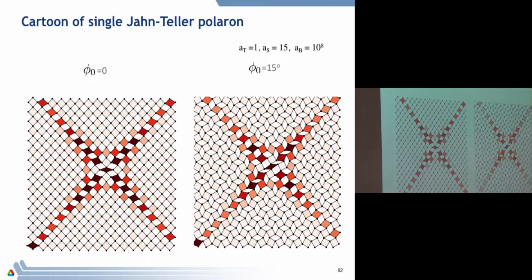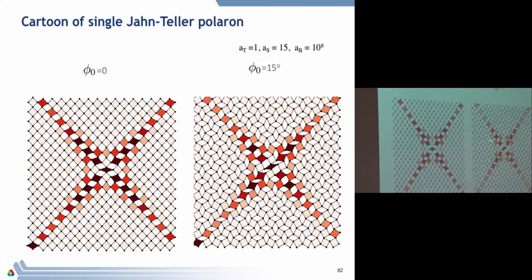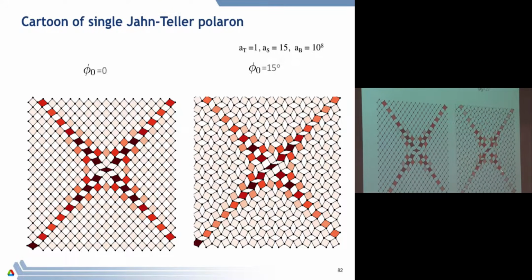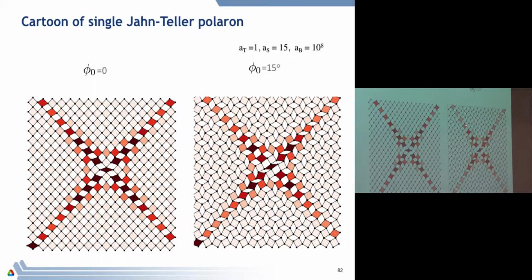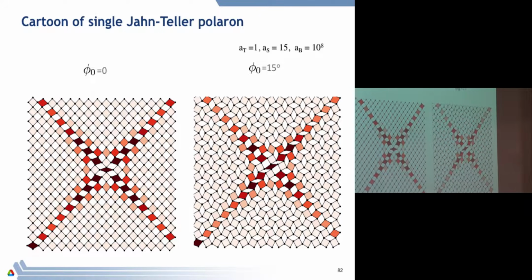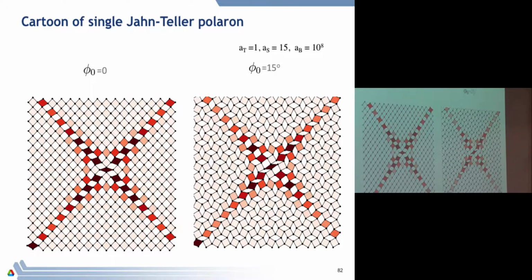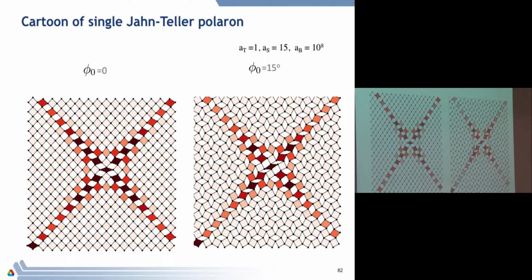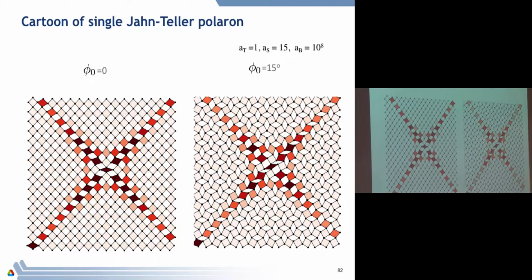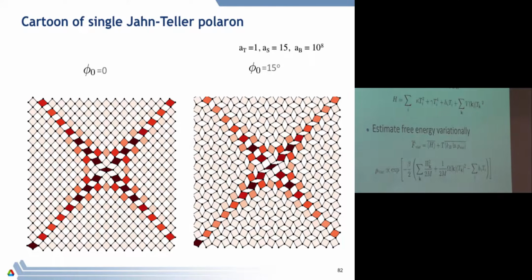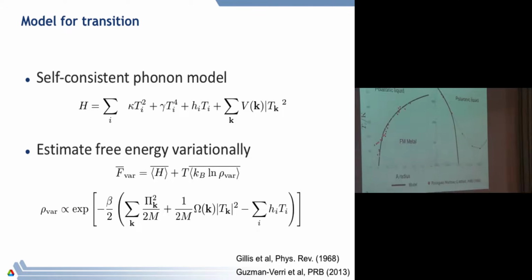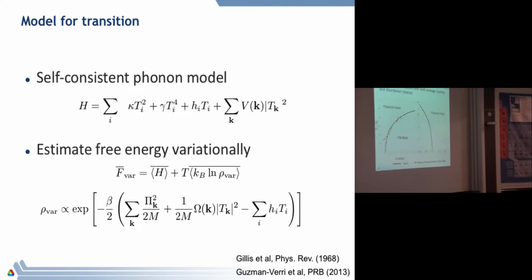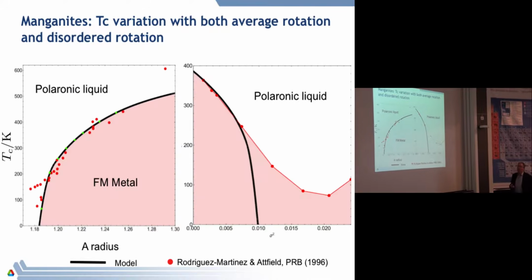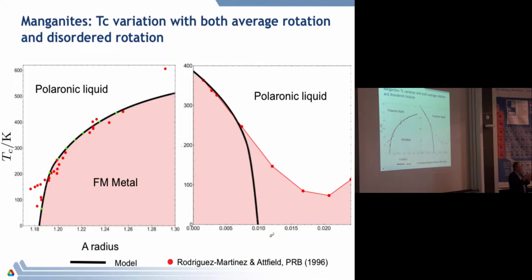If I start with a structure which has some rotations built in, those strain fields die off more quickly, and they're absorbed more effectively locally. So this thing is lower energy than that. It's easier to make. You can make a theory of that. And this is the outcome of the theory. It's not a very complicated theory. It has only elasticity in it.